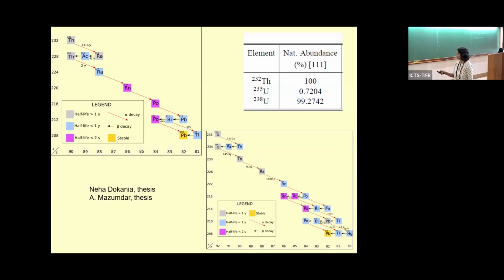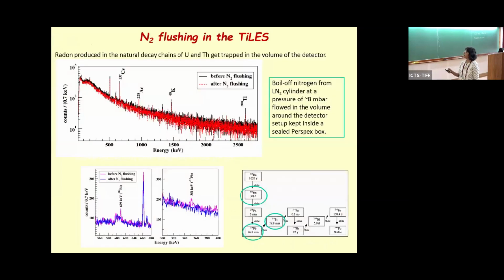Here you have the 222 radon decay. If you look at this line, which is coming from the bismuth isotope, it is present, and after you do the nitrogen flushing, you can see that the line is gone. You can actually see that with 15 days of data, one month of data, and so on, it reduces. That's important, because otherwise that stagnant background builds in. We are interested in the region near the Q value, but the low energy background can also pile up and add to the background.